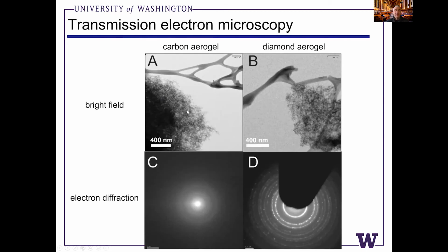We can recover the material from the diamond anvil cell. This is amorphous carbon that's been pressurized but not laser heated, and do electron diffraction. It still looks very amorphous in its electron diffraction. If we laser heat the carbon aerogel at high pressure, we can recover that material and look at the electron diffraction.